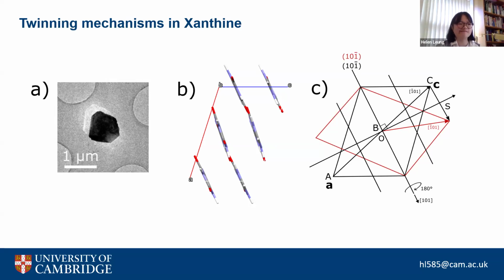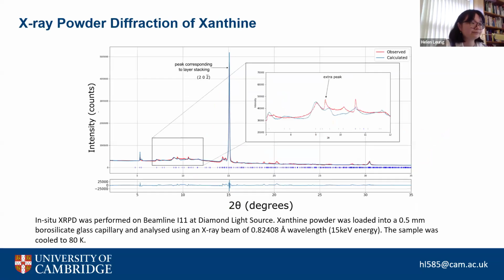So that was really interesting to see. So we thought, okay, maybe this explains a lot of what we're seeing in 3D ED. Maybe that will make sense. However, when we took this to X-ray powder diffraction, because of course we're working from a powder sample, we can also take some of that sample and put it. And we went to the Diamond Light Source, and we went to the beamline I11, which is high-res XRPD.